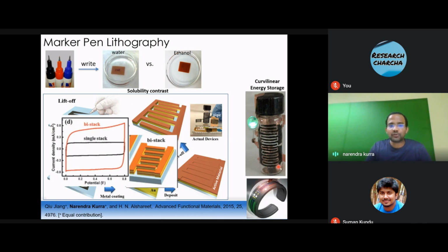And we have also shown that we can build multi-layers using this approach, and then increase the areal capacitance of the device. A single stack means one active layer, and a bi-stack means you have two active layers, with which you can enhance the energy density without compromising the power density. That is the advantage of this unconventional marker pen lithography technique.